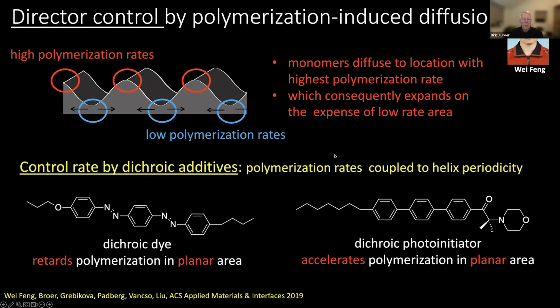Well, having these liquid crystal orientations in place, we can control this by dichroic effects. For instance, you can add an azo dye into the system. An azo dye orients with the planar, with the orientation of the liquid crystal. So in the planar state, it will absorb the light that is also needed to initiate the photopolymerization process. So locally, we will have a lower polymerization rate where the dichroic dye molecules are oriented in a planar way, which means that in the areas where the molecules are perpendicular, the polymerization rate is higher, and material tends to diffuse to these areas.